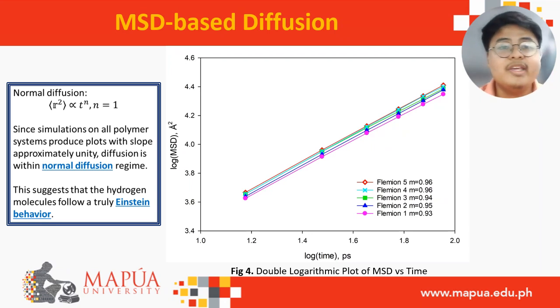When modeling MSD-based diffusion, it is important to determine if the diffusion being modeled is under the normal diffusion regime and not an anomalous diffusion. The normal diffusion regime is described by the following power law, where the mean square displacement should be directly proportional to the time raised to n, where n is equal to 1. Here in figure 4, we can see that since simulations on all polymer systems produce plots with slope approximately unity, diffusion is within the normal diffusion regime. This suggests that the hydrogen molecules follow a truly Einstein behavior, which means that the diffusion that was modeled was not anomalous, but rather it was truly random.